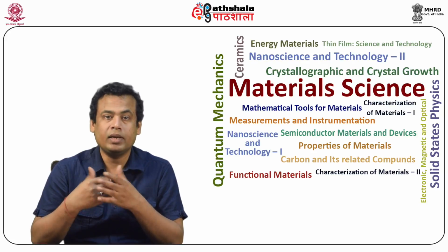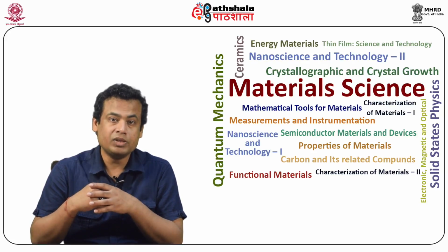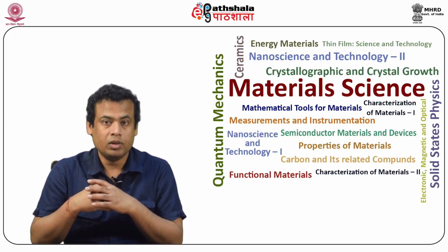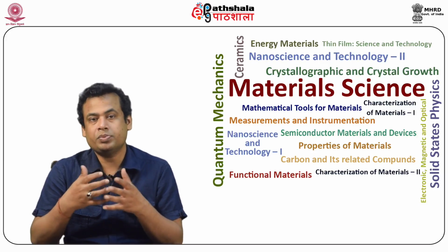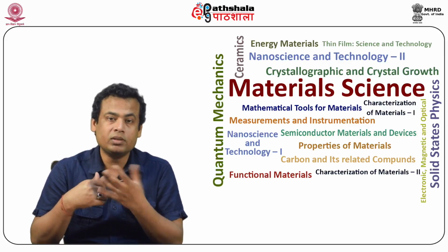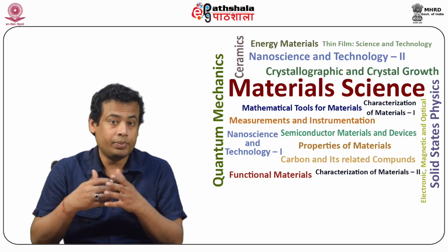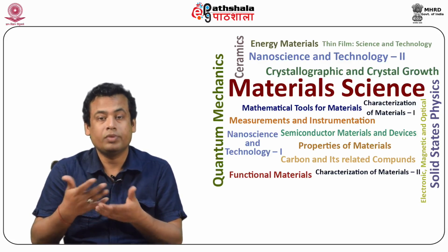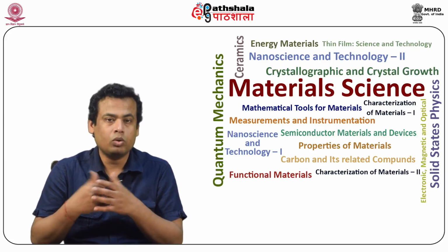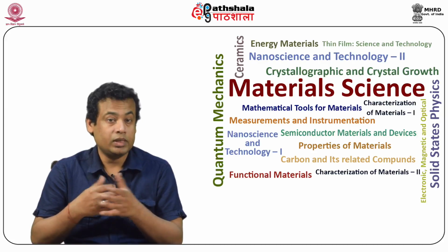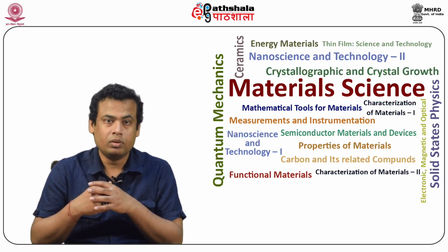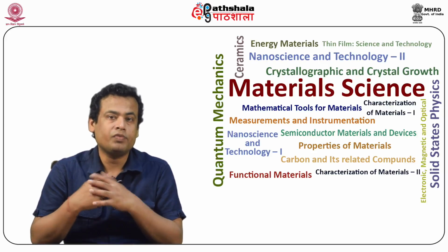The first kind is electrons located in the valence or conduction band, which are loosely bound outer electrons and need only a small amount of energy transferred to overcome the work function and be ejected into the vacuum. Typically, they carry energies below 50 electron volts and are thus designated as slow SEs. These secondary electrons are utilized in the scanning electron microscope for morphology and surface topography studies.